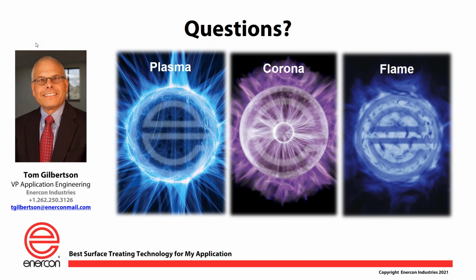Keep in mind something, folks. The corona treater, gas flame treater, and plasma treater are just treating the surface of this product. They're only going a few angstroms deep. How that product was created, the additives in it, the extruder temperature, the winding tension, the environment the film was kept in after it was made, and the cooling all matter. If it's a blown film, what was the bubble cooling like? What's the cooling method in the OPP line? How do they control it? Is it tightly controlled? Was it not operating properly at the time? Those things may sound incidental or not connected, but when you're talking about surface treatment, they can all be connected.